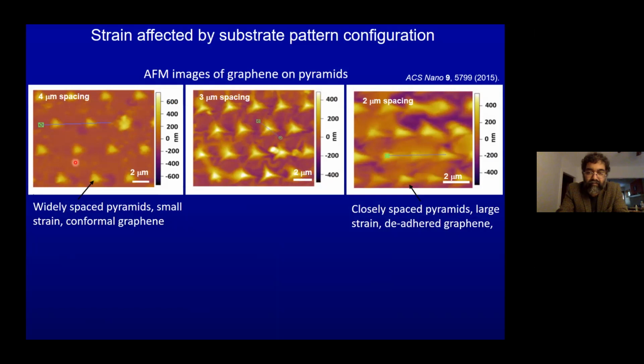And so here you see 3 atomic force microscopy images, where the left one is for the far spaced pyramids and the right is for the more closely spaced ones. And you can see on the left, there's almost no features actually. What this is telling you is that for the widely spaced pyramids, the graphene basically conforms to the pyramids, okay? Because it's not very strained, so it just kind of lies over it like a very soft blanket, okay? However, as you start making the spacing smaller, you start seeing these bright lines in between. See those wiggles there? Those are wrinkles that are formed, and it tells you that the graphene is starting to be strained on the pyramids, and it's releasing the strain by forming wrinkles in between.